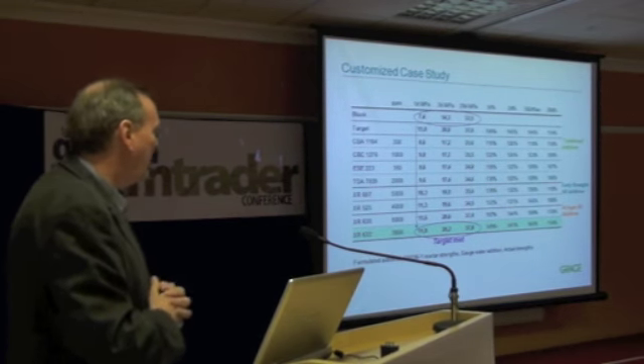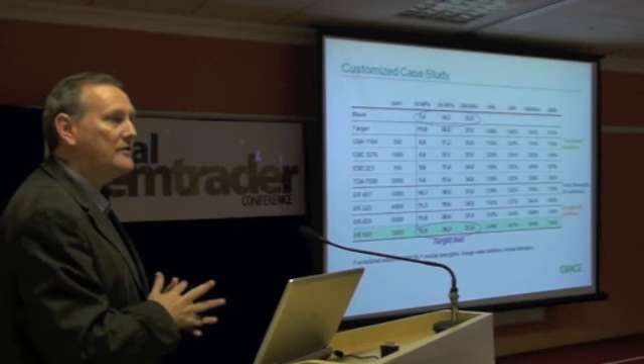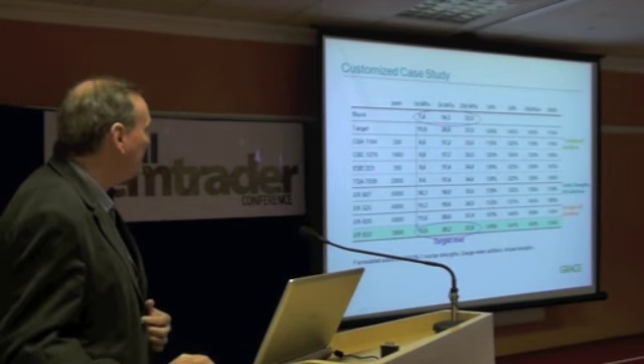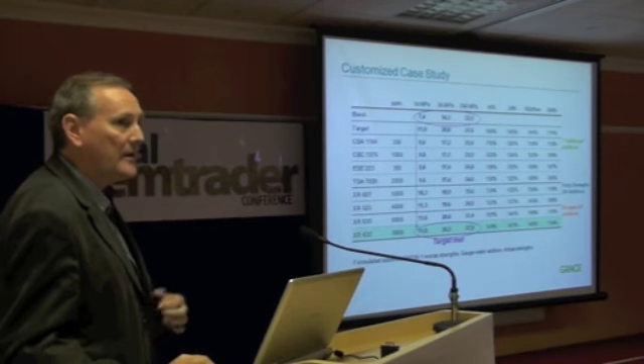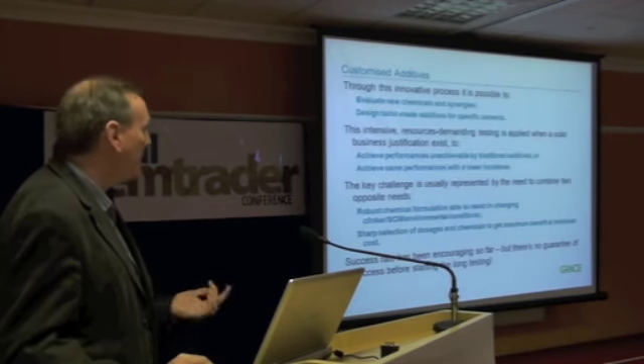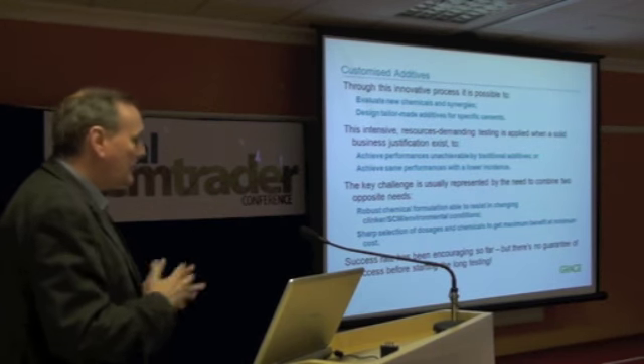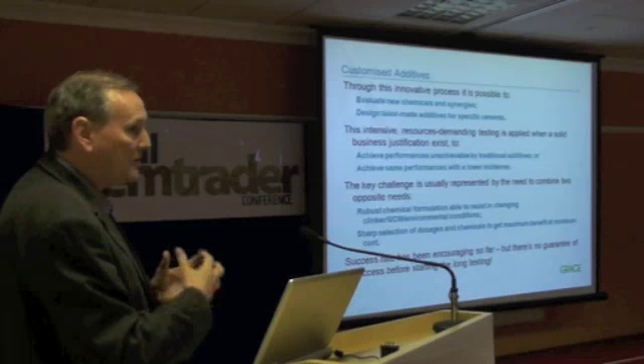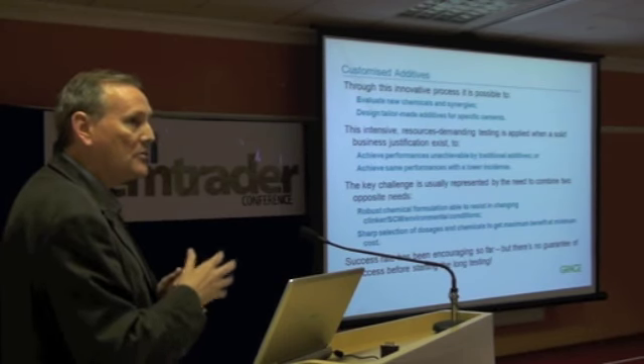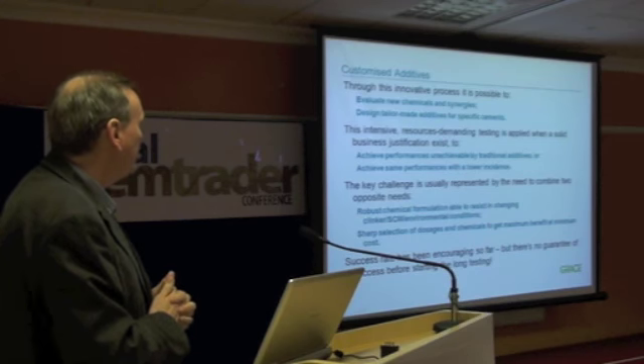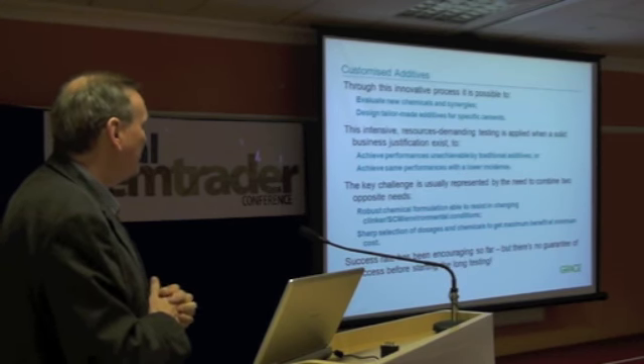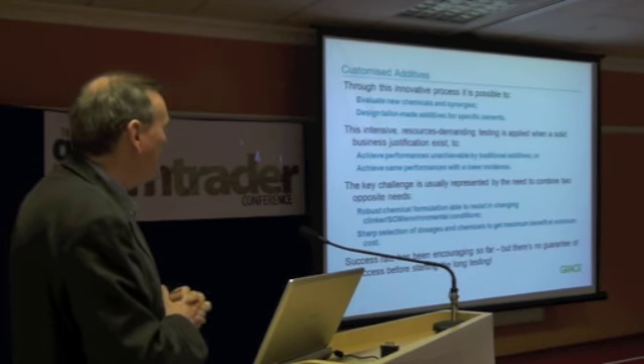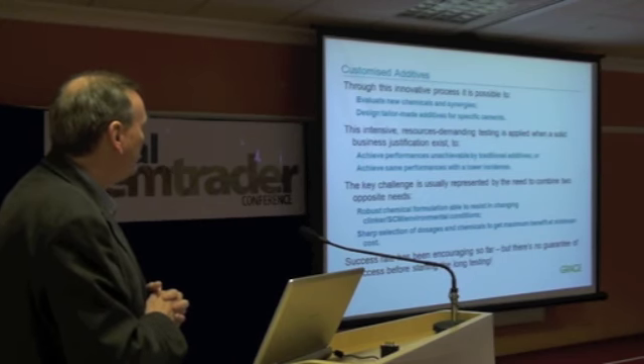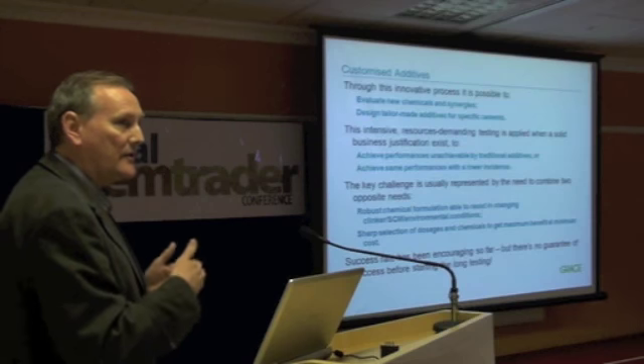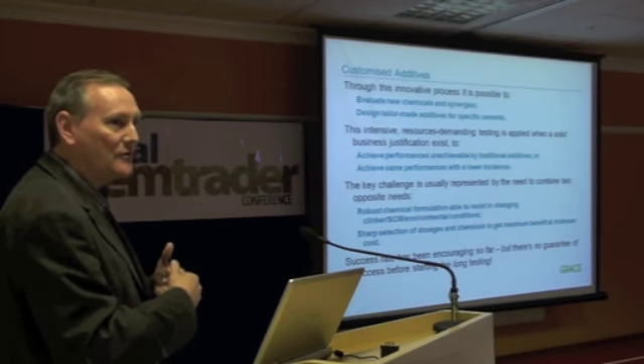But that's an example of where, by systematic customisation, you could reach higher targets, and that's more or less the summary of where we've reached: if you want very good results, you need to work a bit harder and customise. So we can also use this to evaluate new chemicals and synergies between chemicals, and synergies between the chemicals and the cements. And we're getting tailor-made additives for specific cements. It is demanding, so we're not going to apply it everywhere. But we are getting to achieve performances we didn't get before, and we're also getting it to achieve the same performance at lower cost. Basically, just try to formulate cost out of the system to give the same results.